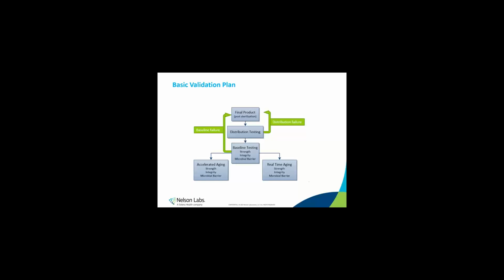And that's not really great because you want to be selling your product. So you can use accelerated aging at temperatures up to 55 C to speed up the process. It only takes 7.5 months to get a 5-year accelerated age product. You can submit to the notified body with just the accelerated data, but you're required per ISO 11607 to start the real time within 3 months of the start of the accelerated portion. And this is really just to ensure that the real time isn't forgotten.